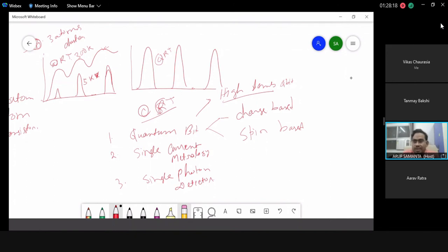Room temperature energy is around 25.6 millielectronvolt. So it's 200, and this creation is very difficult. To create such a thing, you have to go for the size of the quantum dot. The smaller size should be of the order of 2 nanometer. And this creation is really difficult. Okay, sir. So you have to be an expert in how to create such a gap. That's the two important things I want to say.